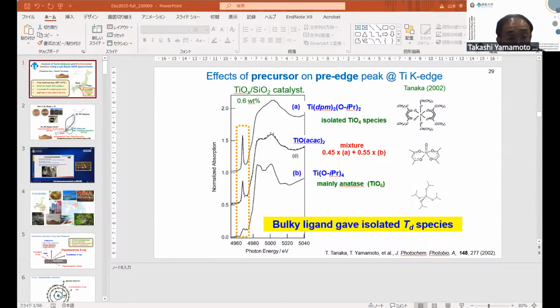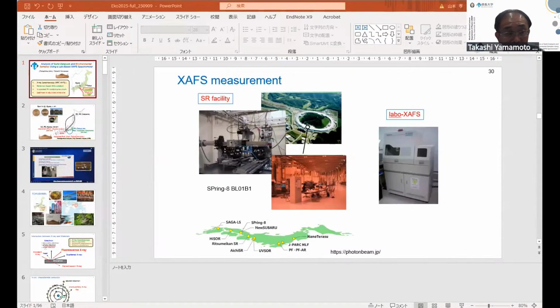Using this complex, the pre-edge peak intensity is half, and this spectrum can be reproduced by the combination of the A and B spectra, almost half and half. It means a mixture of isolated tetrahedral species and aggregated octahedral species. So by comparison of the XANES spectra, we can know the information about the chemical species or coordination environment like this.